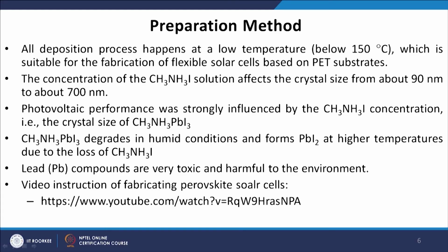The concentration of the CH3NH3I solution affects the crystal size from about 90 nanometer to about 700 nanometer. Photovoltaic performance was strongly influenced by CH3NH3I concentration, that is, the crystal size of CH3NH3 lead iodide. CH3NH3 lead iodide degrades in humid conditions and forms lead iodide at higher temperature due to the loss of CH3NH3I.